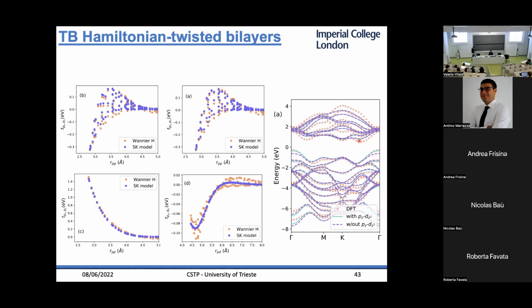What about the folding? Since you have these very big zones, is it a problem to unfold the band structure? That's a good question. Basically, what we do is we have this very large Moiré cell, which contains 1,000 atoms, and then we fold back states at M and K, for example, onto the monolayer M and K. So there is a folding back onto the larger states. But because of the geometry of the system, this is quite simple.